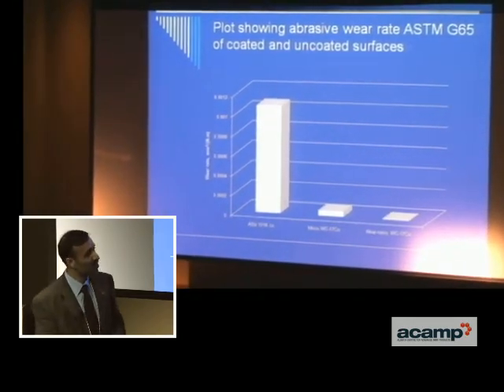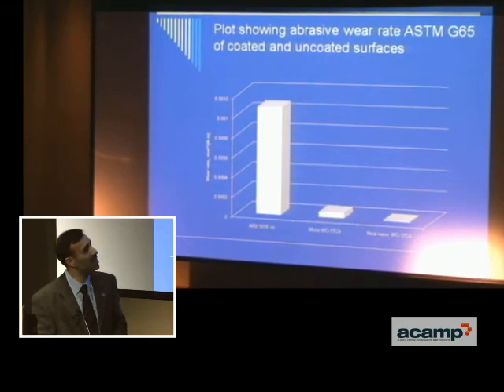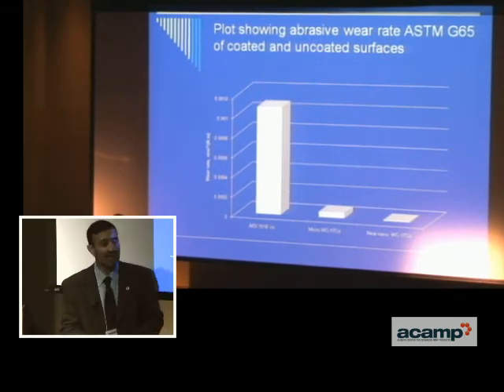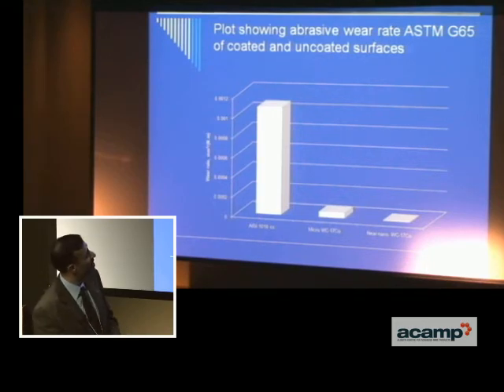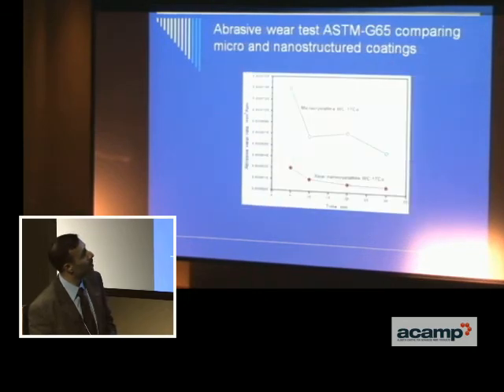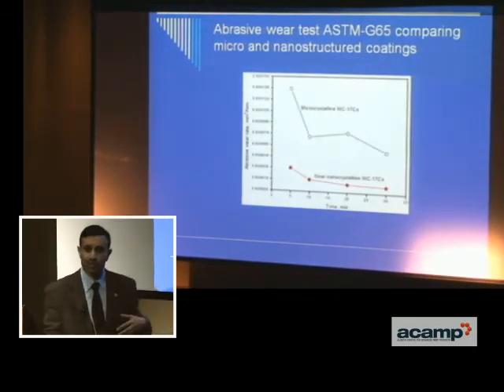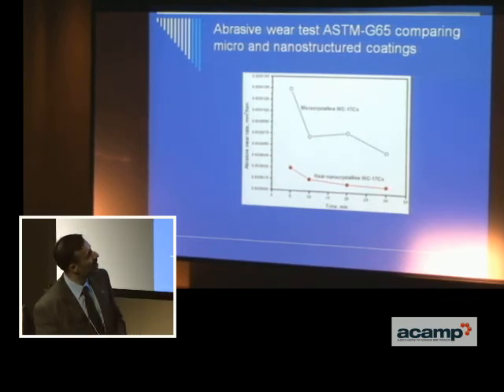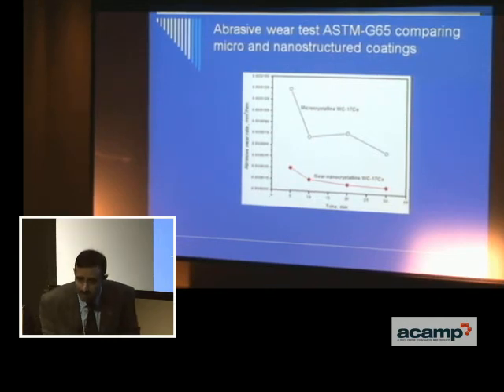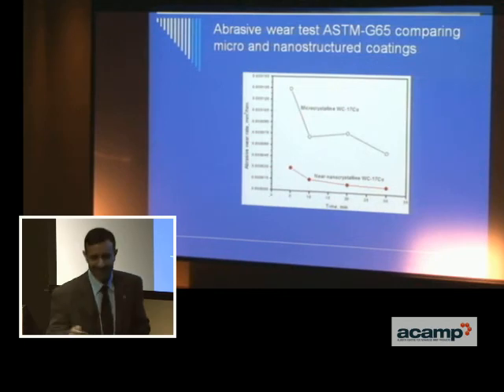If we look at the abrasive wear resistance, ASTM G65 is one of the industry standard tests. This is the heat-treated material, the microstructured coating, and then the nanostructured coating itself. So there's a substantial difference between what tends to be used in industry currently, and the microstructured and nanostructured material. If we just compare the nano and the microstructured powders, we tend to find something like a 6-fold increase in the abrasive wear resistance of the powder.